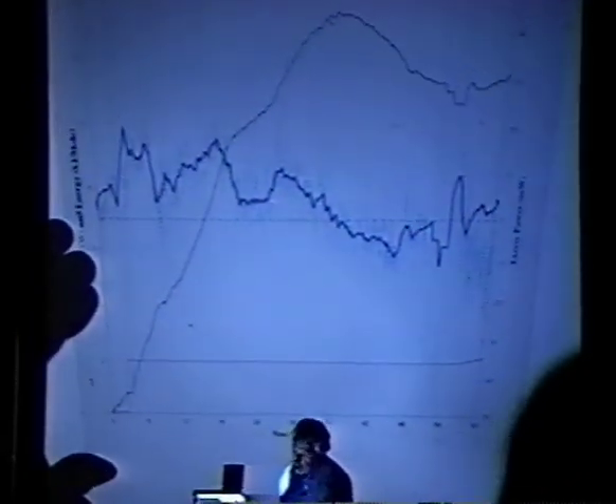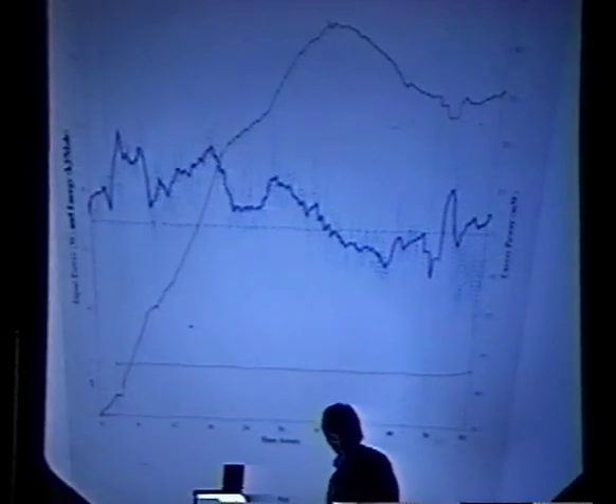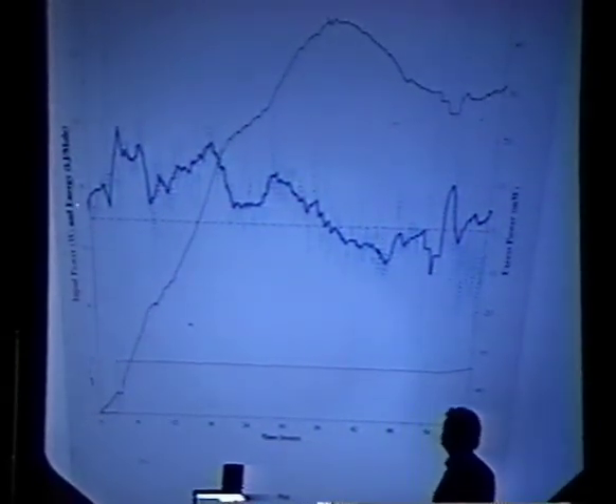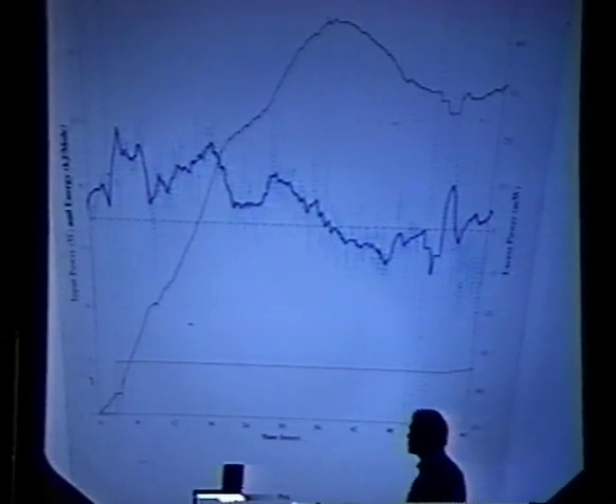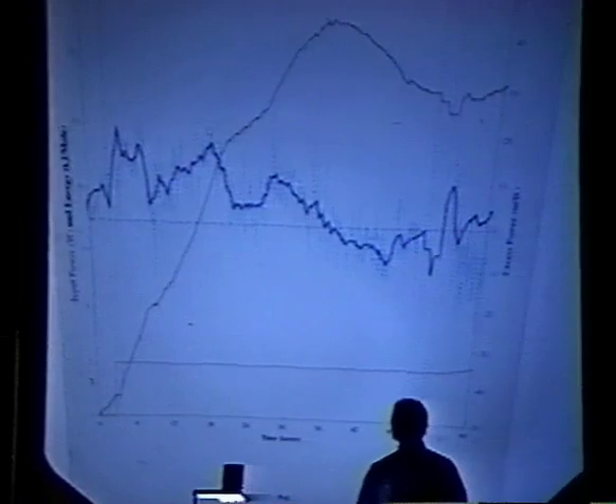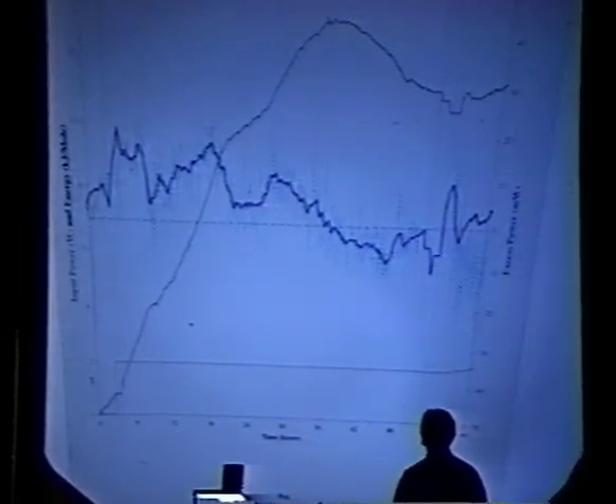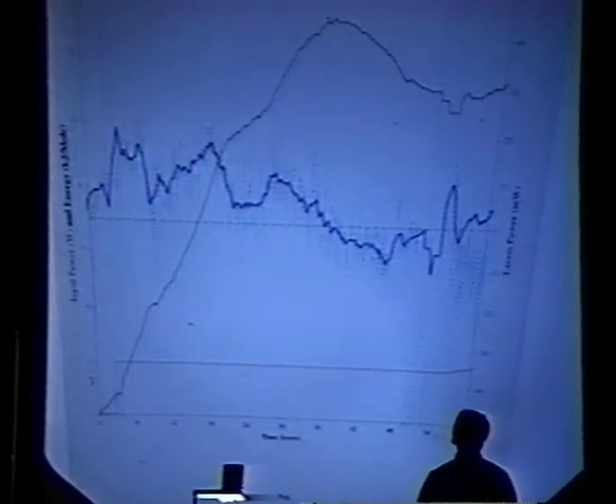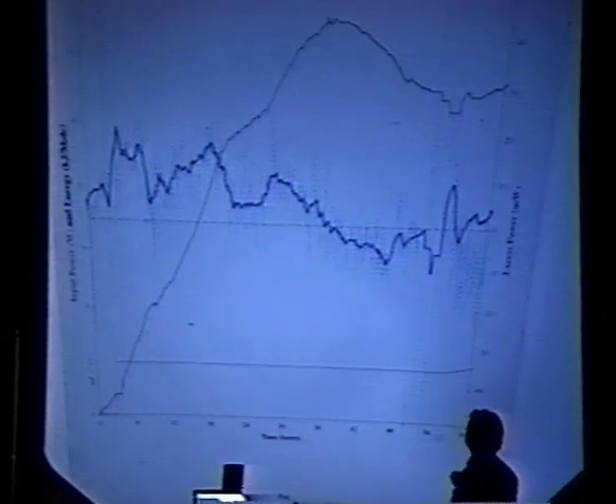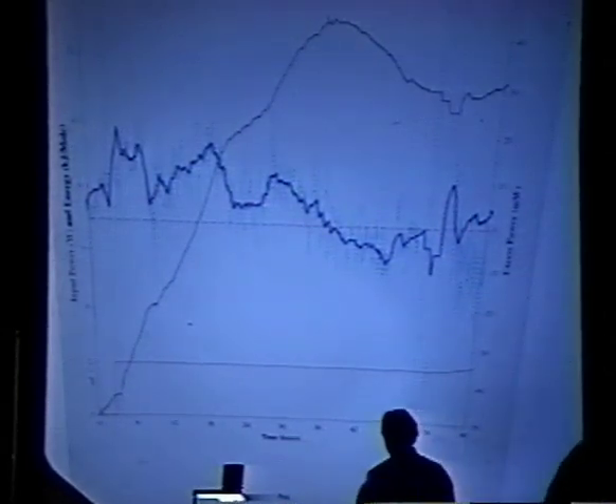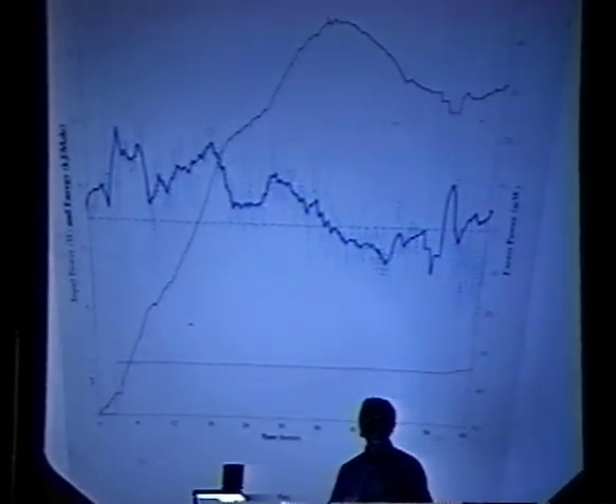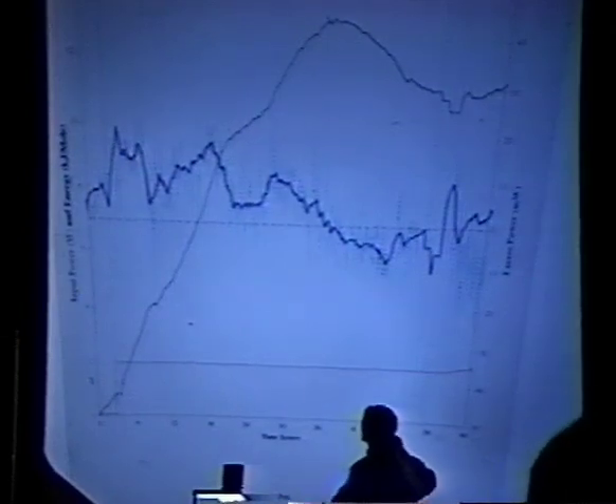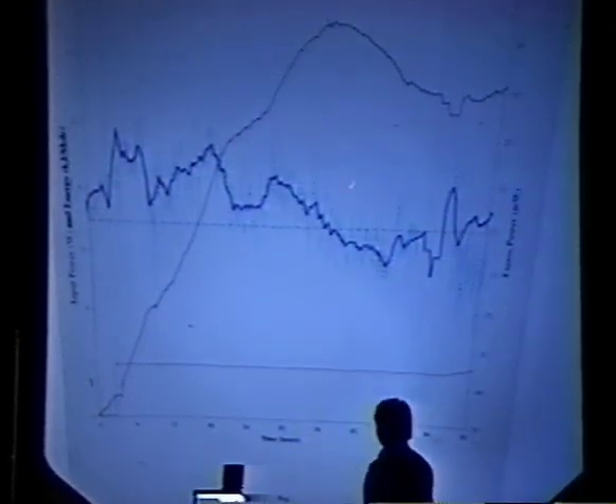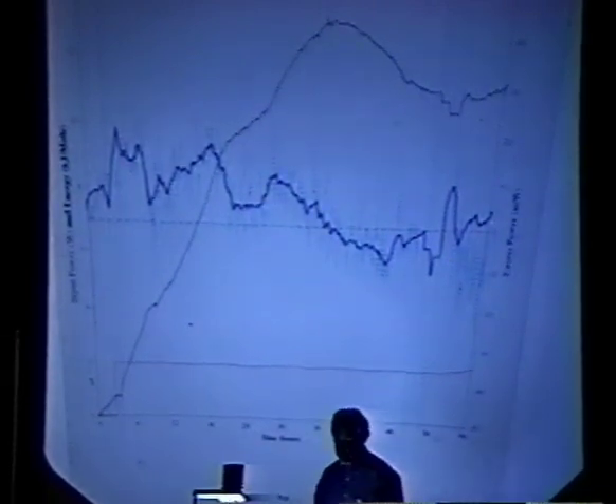We were doing calorimetry. This will also be the smallest excess power result ever shown. All we observed from that cathode, and this is plus or minus 20 milliwatts we're talking about, is that this excess heat here is simply the heat of absorption of deuterium into palladium. This is entirely chemical energy. There was no excess heat associated with this experiment at all. Everything we saw was chemical, like 13 kilojoules per mole. So although we obtained quite a high pressure inside the Arata-Zhang cathode, we did so for only a very fleeting moment, and there was no obvious excess heat associated with that.